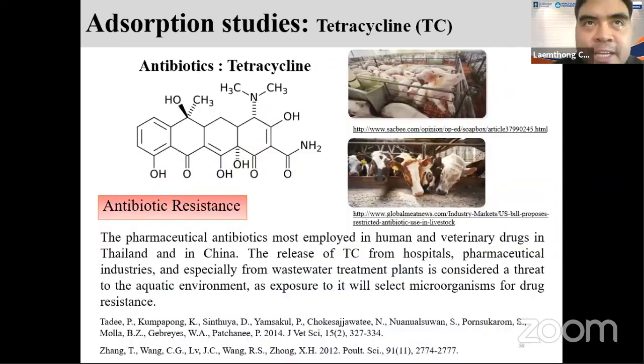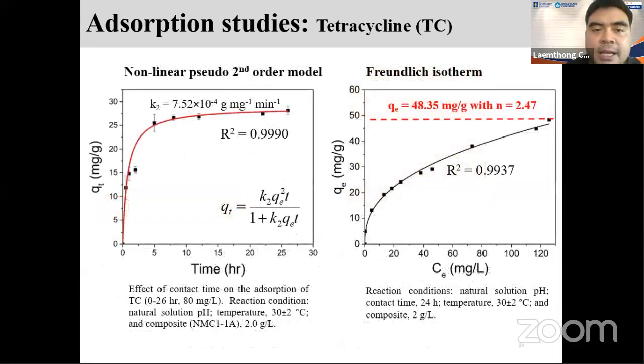So we do it with tetracycline because this is our problem in our country as well. Because we have cattle, and they use a lot of this kind of medicine or antibiotics, the so-called tetracycline, a lot in our country. So it is released into the real environment, and we have to remove it quite quickly. We try to adsorb this kind of antibiotic using the adsorption technique. And we do the batch adsorption technique, and we also do the kinetics.